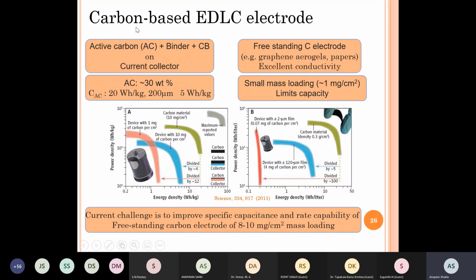So what is shown in this graph is that, for example, here where my cursor is, these are the maximum reported values. But what are these values? As they show here the color, this is for the carbon, which is to say here activated carbon. Okay. Then if you get to carbon material with 10 milligram per centimeter square, your energy density and power density both are reducing. Okay, because you have to keep adding these materials now to make electrode.